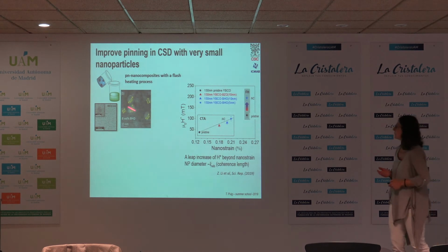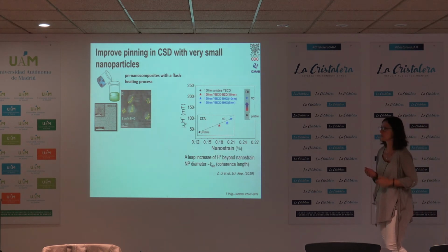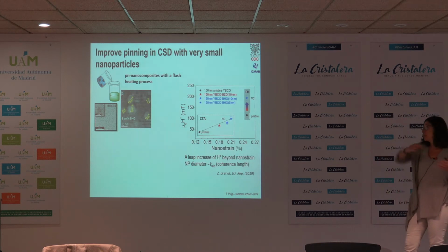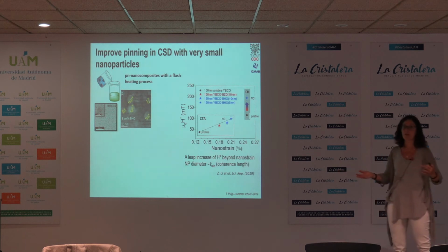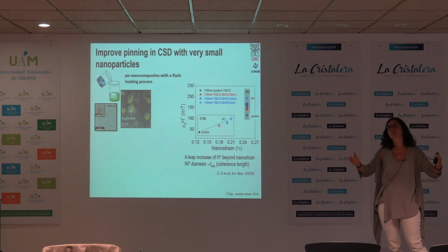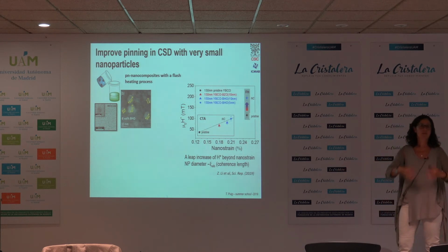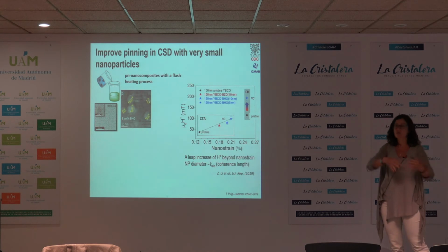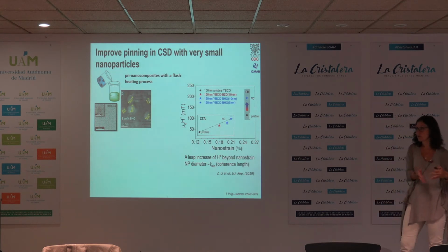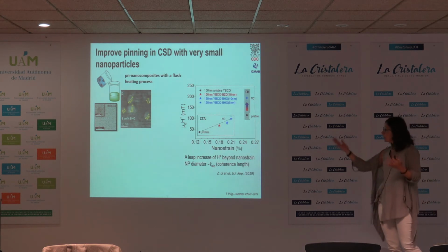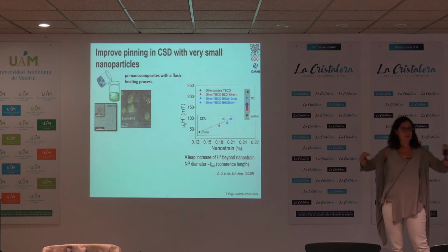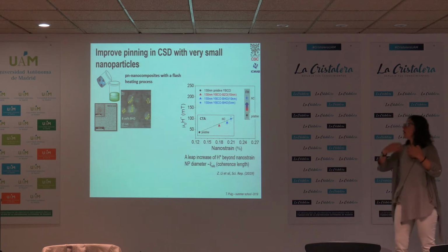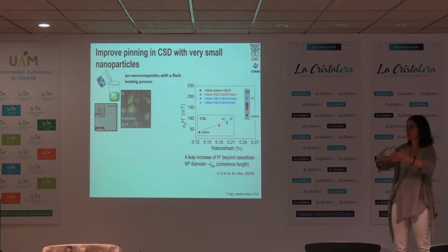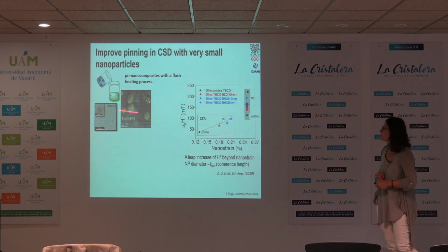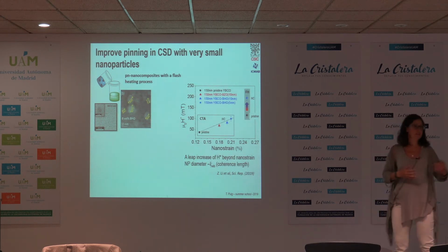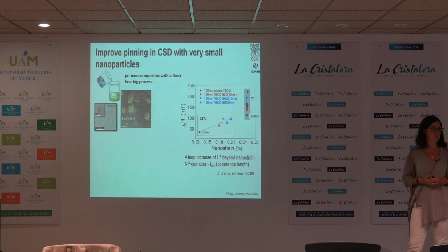Now, more recently, we have been able to decrease the size of these nanoparticles. As maybe I didn't mention before, when you spontaneously segregate these nanoparticles in the material, the nanoparticles end up with dimensions of the order of 15, 20, 25 nanometers. This for high TC is too large to be a pinning center, because it should be on the nanometric scale. However, what we have seen is that it's not the nanoparticle itself, but all these defects and all this strain which is generated around these nanoparticles, due to these nanoparticles, the ones which are doing the pinning sites. But if we are able to encapsulate nanoparticles which are in a range of 5, 6, 10 nanometers, then maybe the nanoparticles also would contribute as pinning centers.